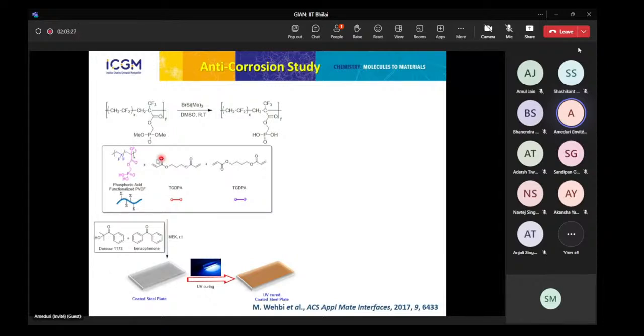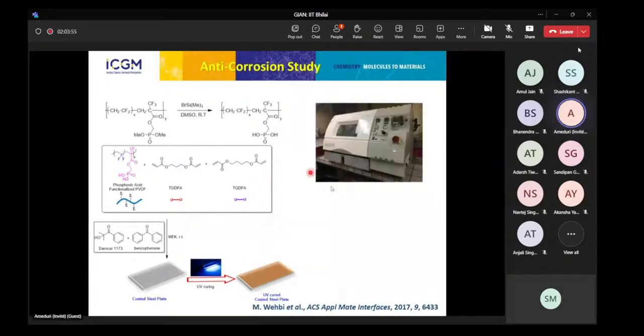You know, when you make diacrylates polymerization, you have a cross-linked material because it's what is called telechelic, and the mixture was added with a photoinitiator, spread on a steel, not stainless, it was a steel, and then photopolymerized to see how the coating was stable or not, and then put in a special machine for salt spray testing, because this simulates the marine atmosphere in very high salt concentration, sodium chloride concentration. So the plaques were immersed, so there was a mist of sodium chloride, and then after reaction, we observe the state of the different plaques.